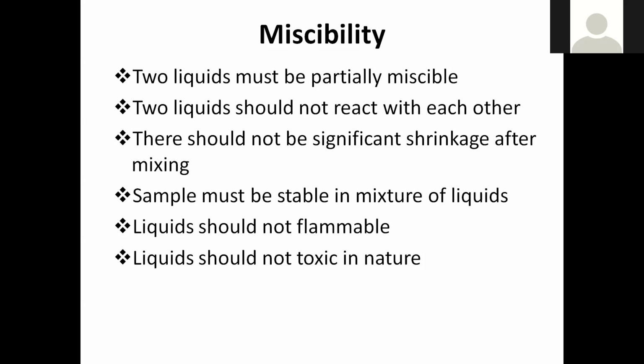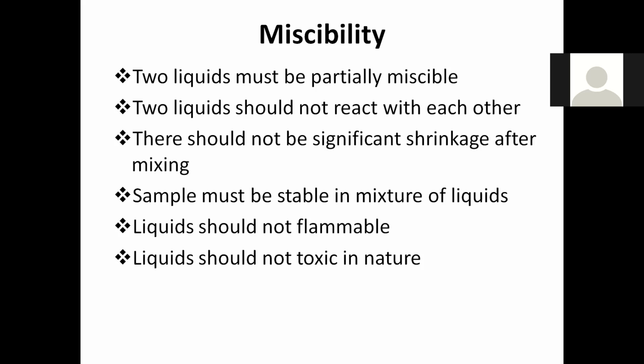These liquids should not be flammable, because this density gradient column needs to be kept in an environment where you have to maintain the temperature of that room or the surrounding of that density gradient column around 23, 24 degrees centigrade. If you are able to maintain 20 degrees centigrade, it is well and good. But in the subcontinental region, if you are maintaining 27 degrees centigrade, it is also permissible.